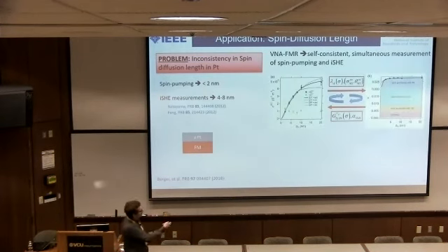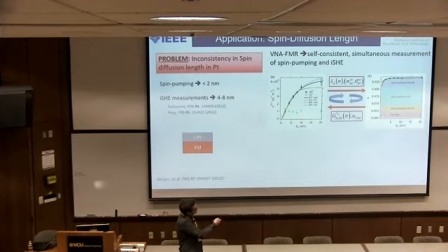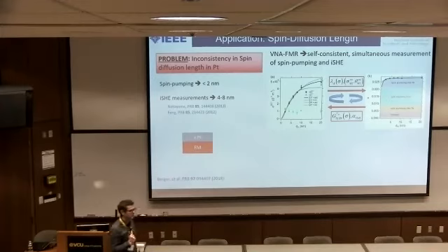So here, using this sort of self-consistent fit, we separate out the different contributions of damping. The red here is the intrinsic damping of the sample, of permalloy. We of course have some spin pumping contributions into the seed layer. We had to use a tantalum layer to get some good growth. And then all of this is due to the platinum, right? Whether it's spin memory loss or spin pumping. And so the intrinsic damping is just a very small part of this whole picture.